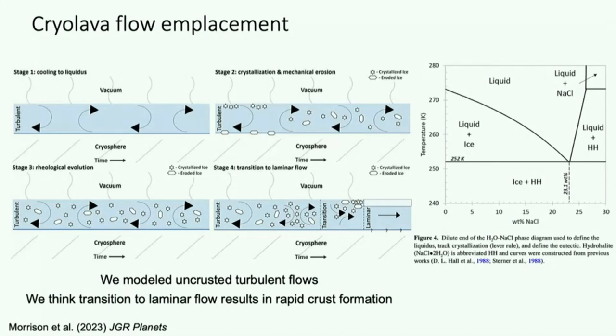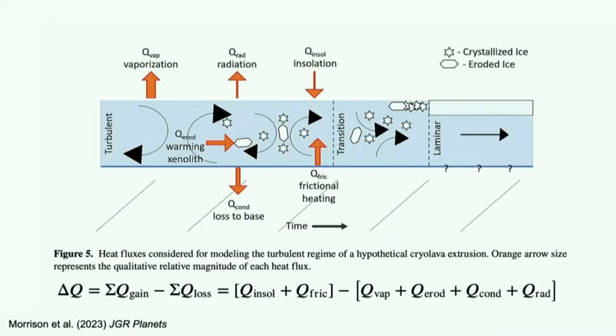It's going to be really turbulent to begin with. It's also going to be evaporating. It's going to start crystallizing. And sooner or later, the effect of the crystals in there is going to make it more and more viscous. It's going to find it harder to stay turbulent, and at some point, it's going to transition to being laminar. All right. So when that happens, the model we're going to use no longer applies because we're assuming turbulent flow for a bunch of calculations, but also probably something dramatic is going to happen at that transition. For a start, once you get laminar flow, the ice crystals can all float to the surface and form a roof very quickly. In turbulent flow, those ice crystals are going to be entrained.